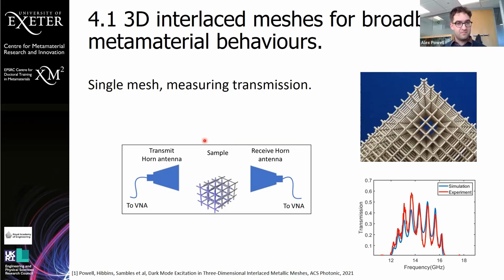Okay, and Max, you stole one of my questions to Alex about high epsilon, but I still have the second one. Alex, it's a bit more detailed. You cover these nice 3D printed structures with some paint. How good is this metal there? Have you somehow measured conductivity, or some other properties? You have very good agreement between simulations and experiment, probably because the frequencies are quite high and the thickness of the metal is definitely larger than the skin depth, but still some issues with conductivity and roughness should be there. Have you estimated whether it is really metal or something else with much worse conductivity?